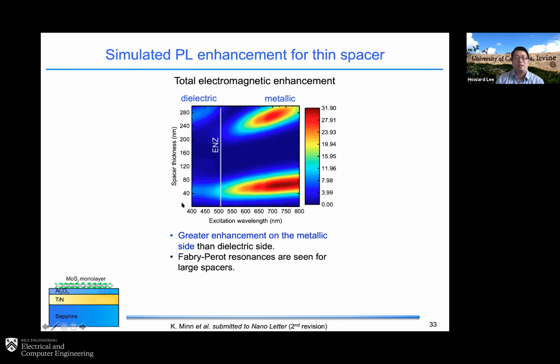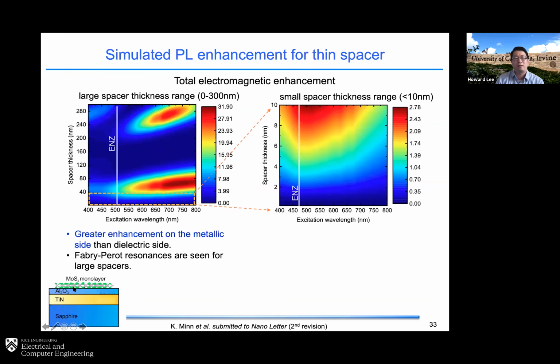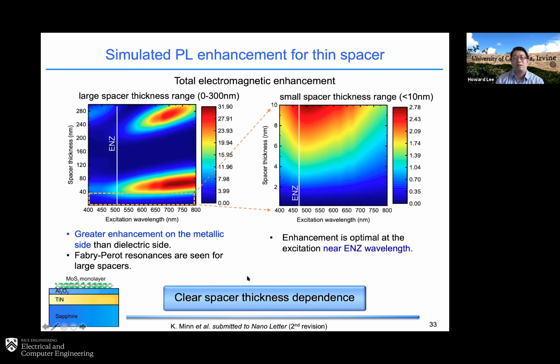But this is for a really large range of spacer thickness, from 0 to 300 nanometers. If you take a closer look at a smaller spacer thickness, the aluminum oxide thickness from 0 to 10 nanometers, you find you actually have certain enhancement close to the ENZ wavelength, which is due to the ENZ material. So you clearly see that depending on the spacer thickness, you may have different regimes, with different enhancement for small and large spacer thickness. Then experimentally, we fabricate with different spacer thicknesses, one small and one thick, and look at the PL enhancement here.